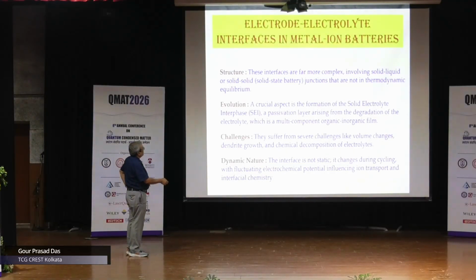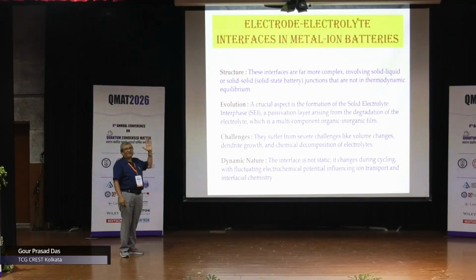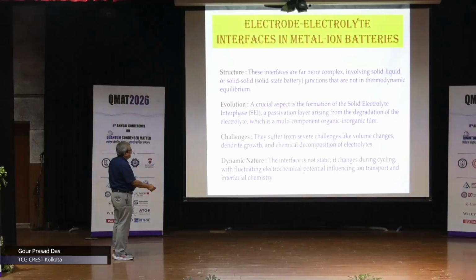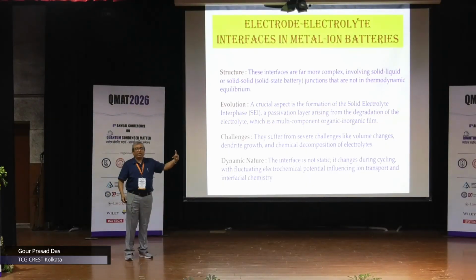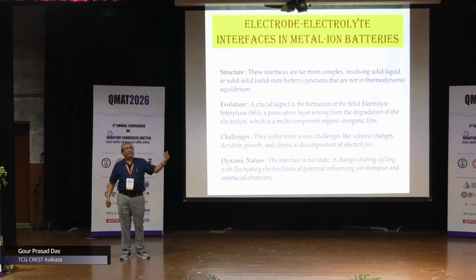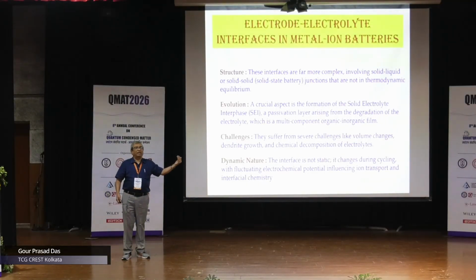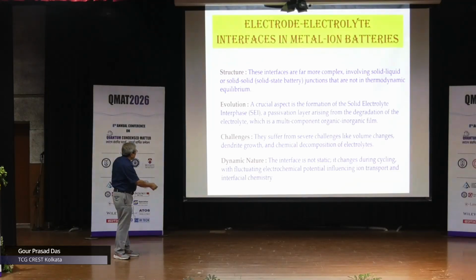Challenges, they suffer from severe challenges like volume change, dendrite growth, and chemical decomposition of electrolytes. We are not facing those in our semiconductor interfaces. Dynamic nature, the most treacherous thing. The interface is not static, it changes during cycling. So yesterday, Tanmoy, my colleague, gave a talk where he showed what happens when the lithium ion goes from cathode to anode through the electrolyte and comes back during charging and discharging. So the interface that is produced has fluctuating electrochemical potential influencing ion transport and interfacial chemistry. This is a dynamic interface, unlike the ones which I showed so far.